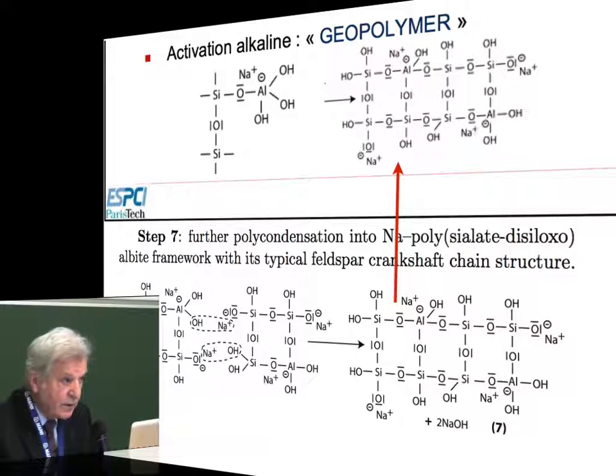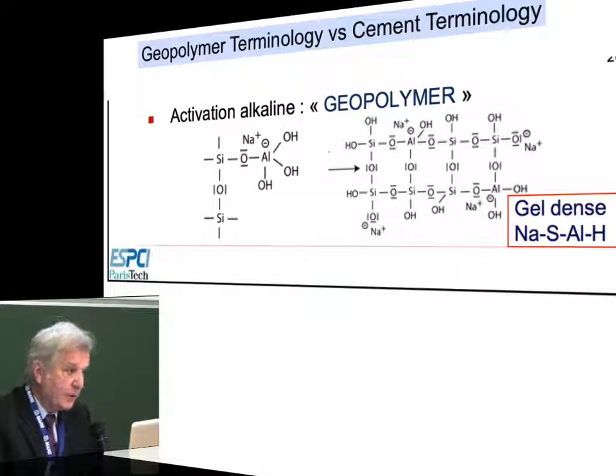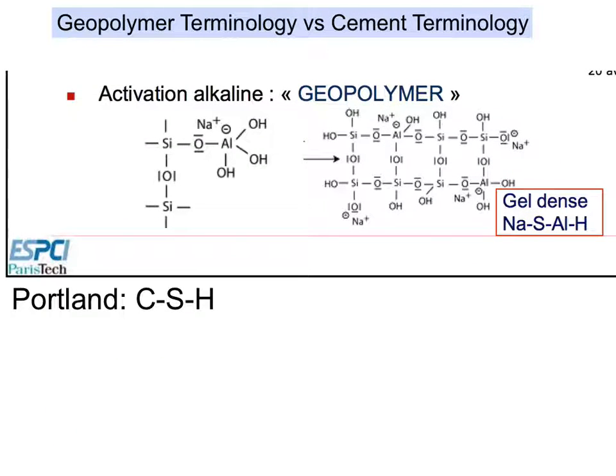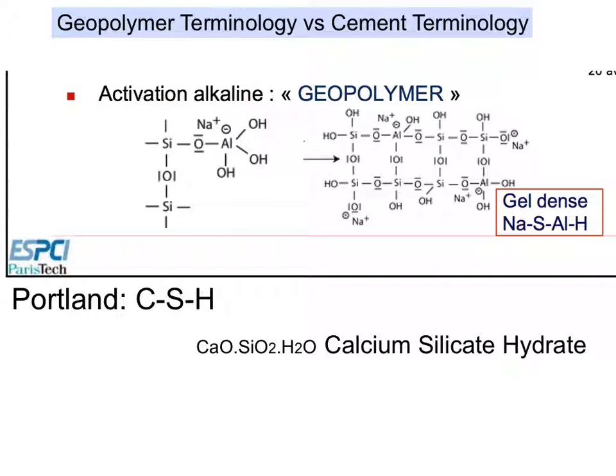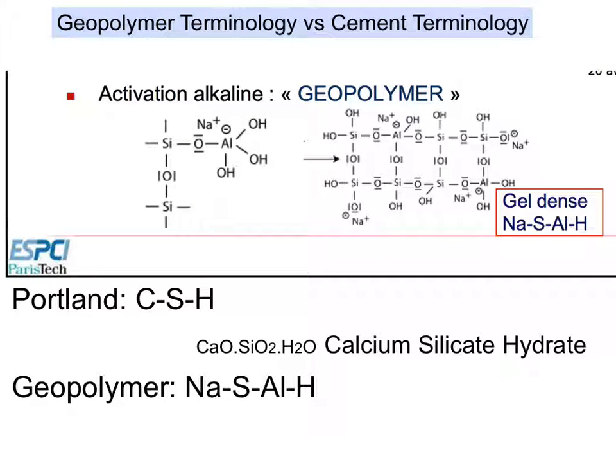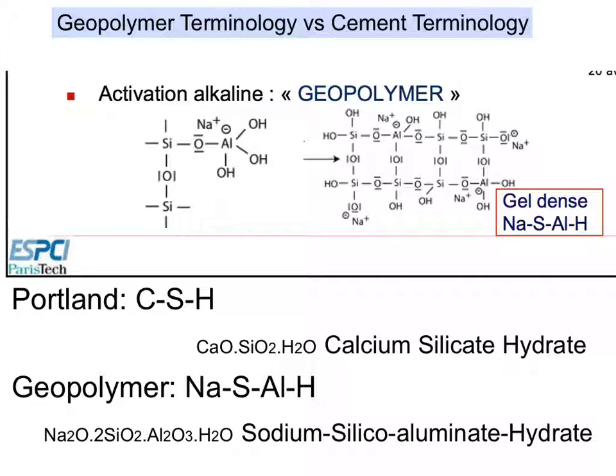After having shown the molecular chemistry of geopolymer, the problem is the following. They are adding the wording from a cement chemistry, and they said, well, a geopolymer is a dense gel that is called NaSAlH. Why? Because they rely on their Portland cement wording. That is, the end or the hardening of Portland cement is CSH for calcium silicate hydrate. And they say, fine, we just shift from calcium to sodium and we get NaSAlH for sodium silicoaluminate hydrate. This is wrong. We don't have an hydrate, we have something totally different.